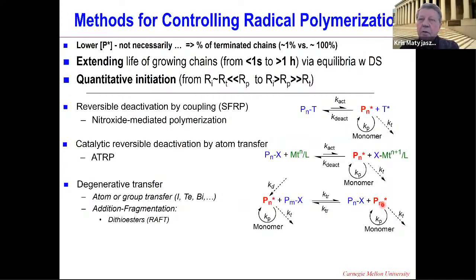However, maybe the most important feature is also the initiation process. We can get in a controlled process quantitative initiation. In a conventional radical process, we have a steady state in which the rate of initiation equals the rate of termination. And in order to propagate 1,000 times faster than terminate, in that case, initiation is also 1,000 times slower. So you cannot have well-defined structures. You cannot make star polymers, which would grow concurrently together. You cannot make block copolymers.